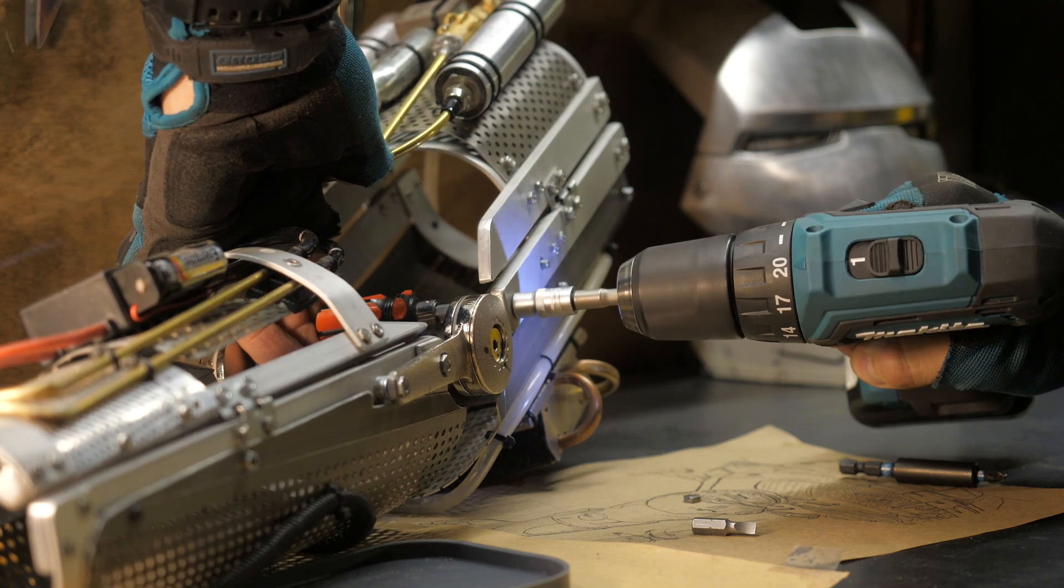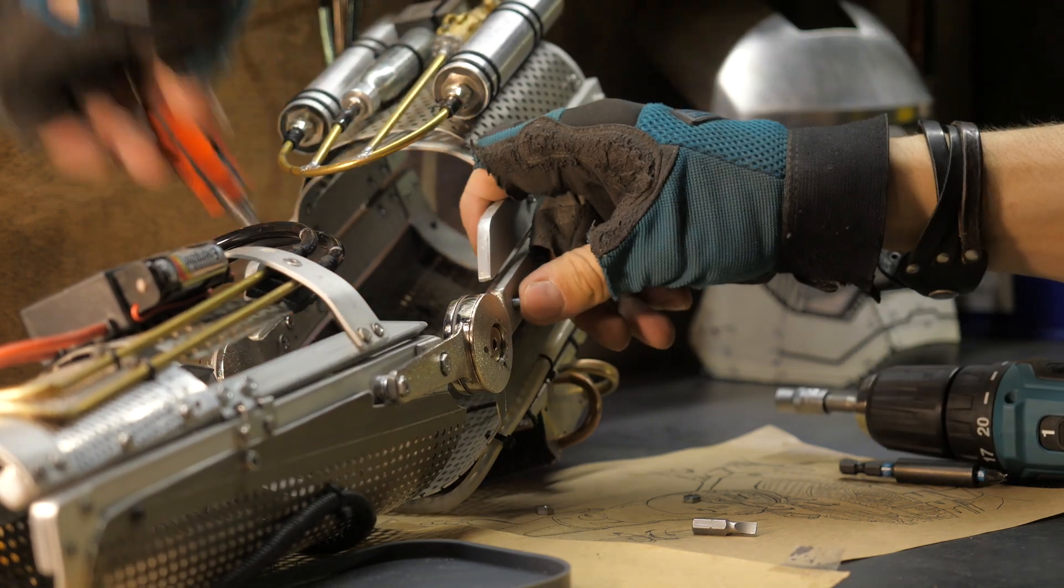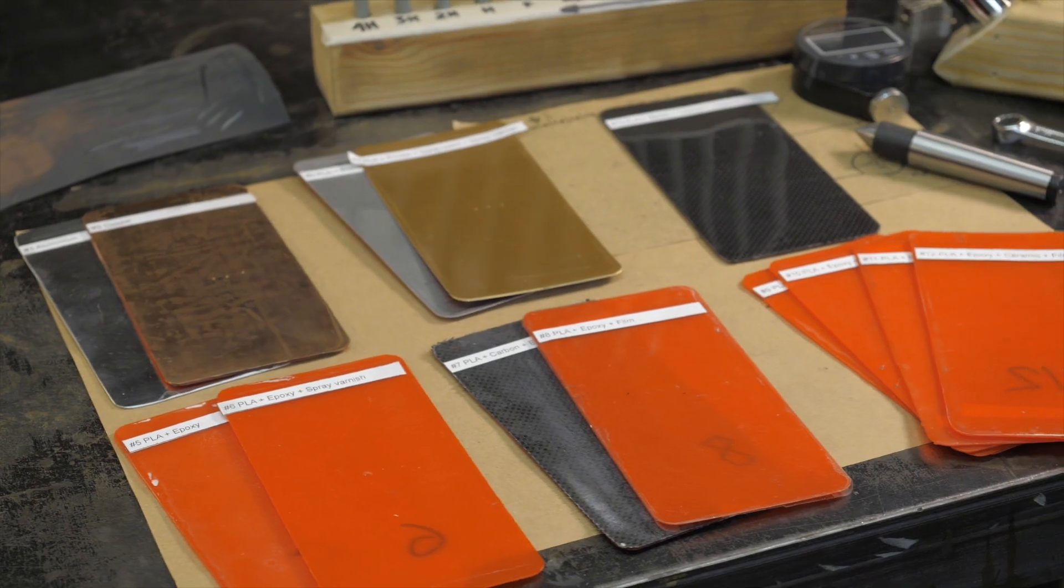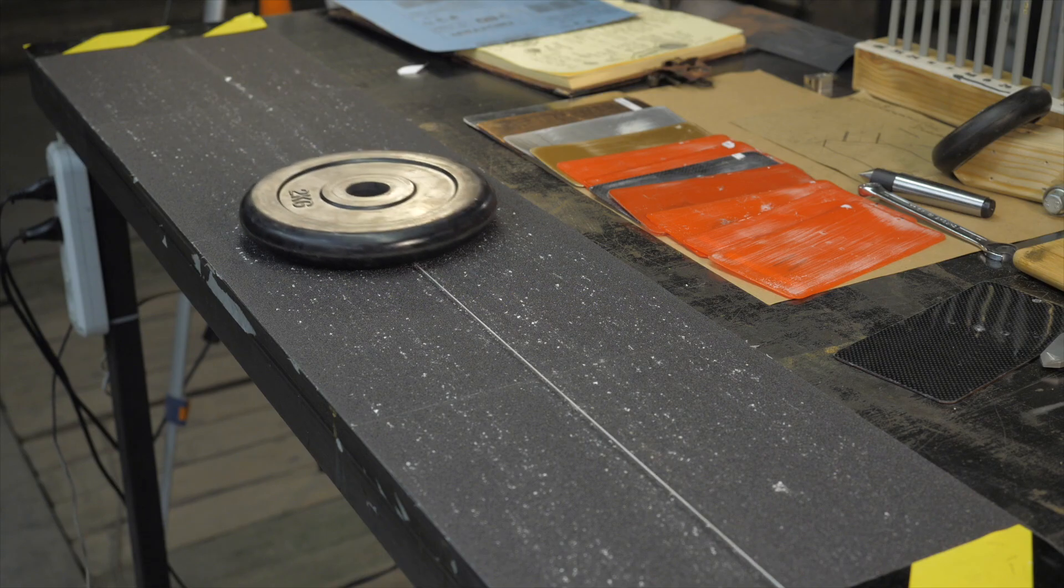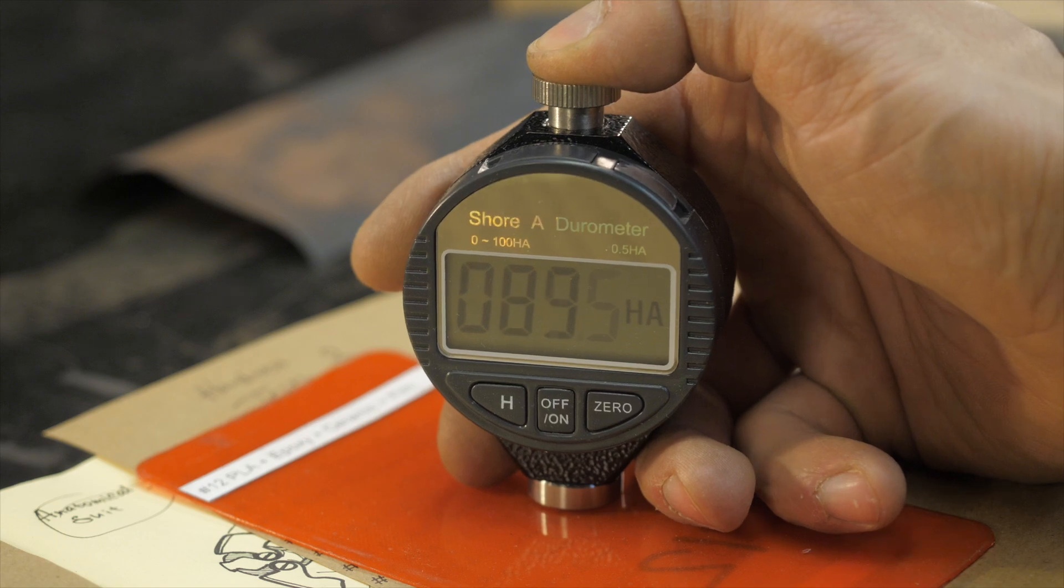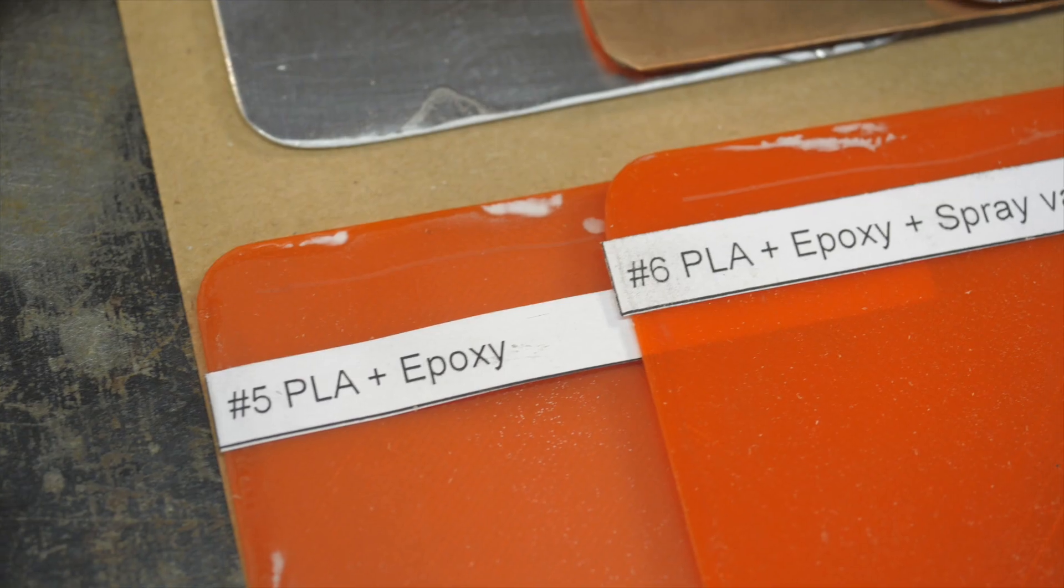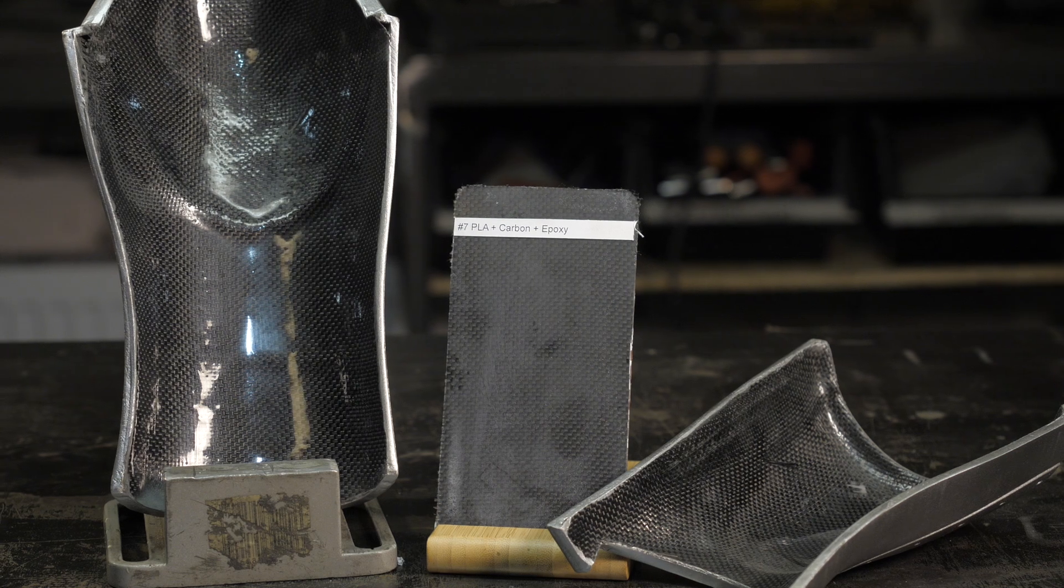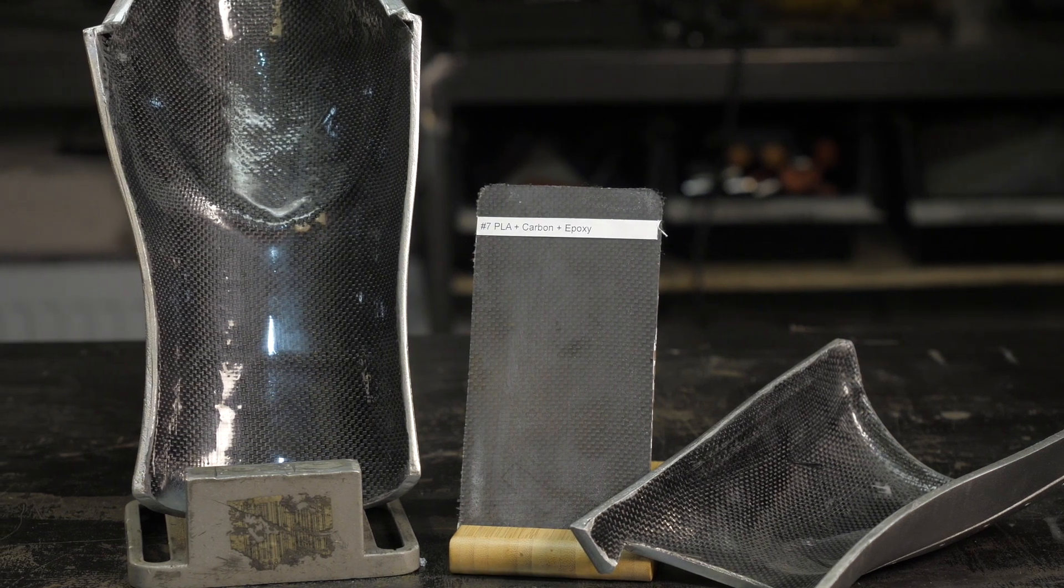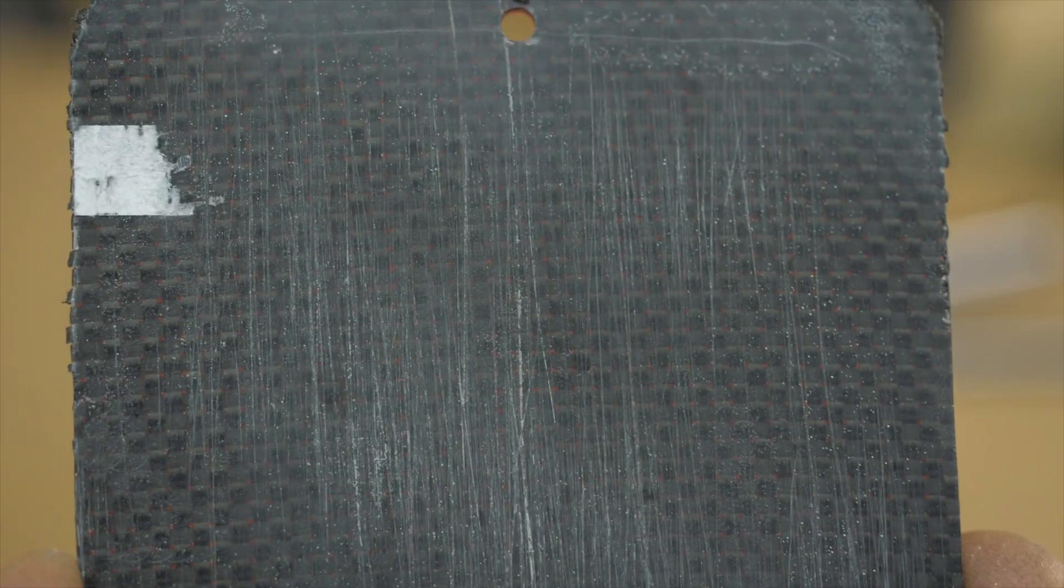Since my field is protective suits and machine parts, then the task of the outer layer of my details is ensure maximum hardness and wear resistance. Hardness tests have shown that the desired hardness give epoxy resin and as more expensive option, giving greater resistance to chips and dents, resin reinforcement with carbon fiber.